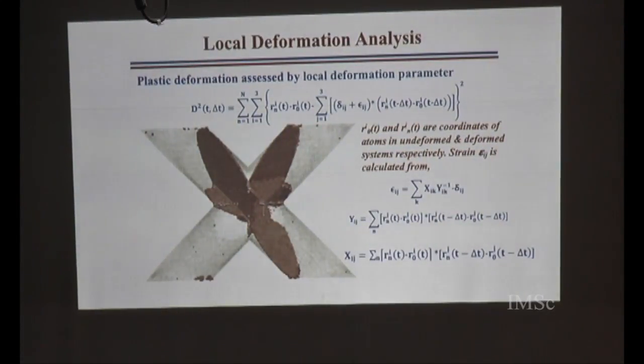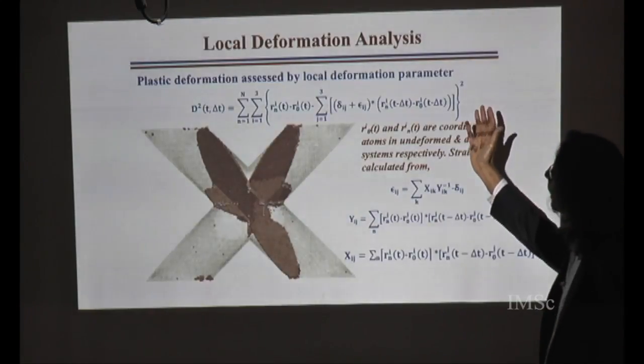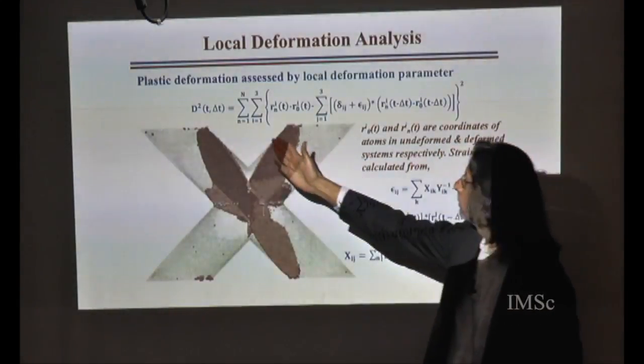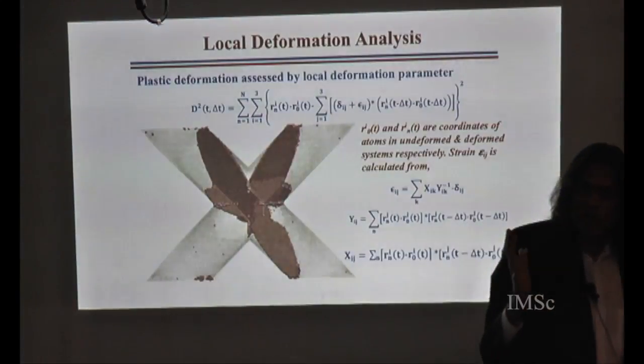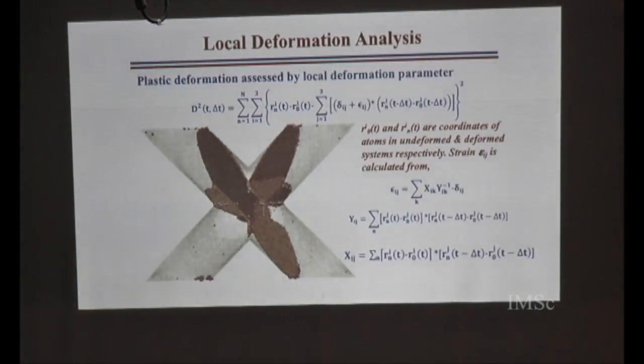Okay. And then we did local deformation analysis on this, okay? And that is, of course, assessed by this parameter, which Michael Falk, I think, introduced. And it's a useful parameter. And then at a local level, we can study what the strain in the system is, where, for example, dislocations are forming and so on. So we have done this analysis on both kinds of systems.